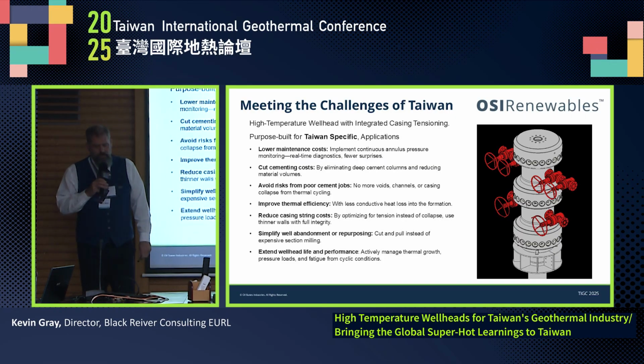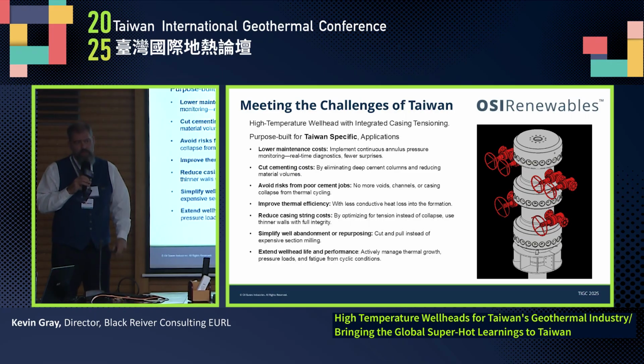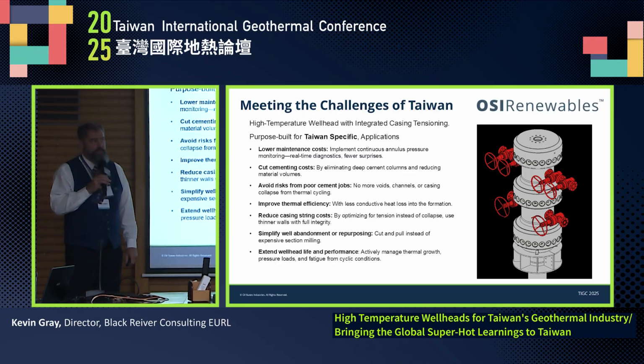And the risks of a poor cement job are voids and channeling that we're unaware of that allows subsurface flows. But if we've got a channel or a void against an impermeable rock, when we heat that well up, that fluid will expand and collapse the casing. So we potentially have a higher potential for failure within that environment.